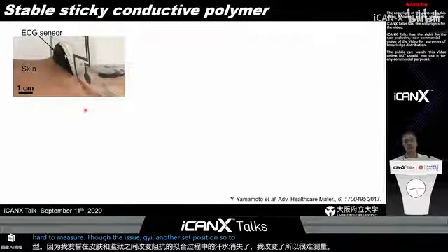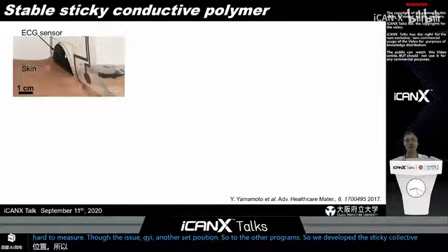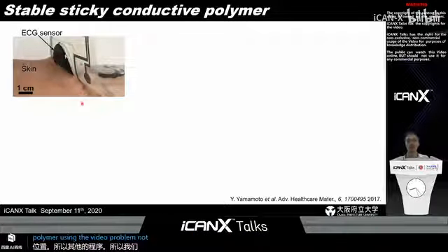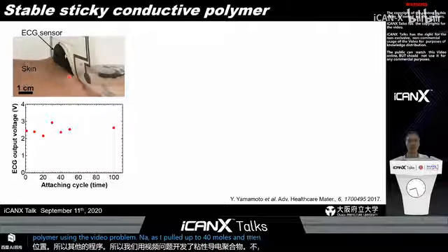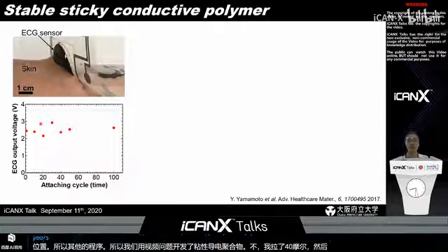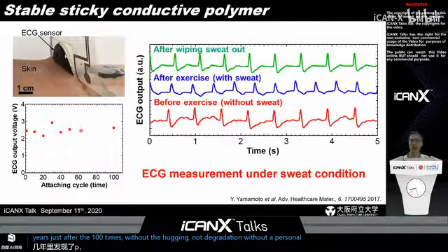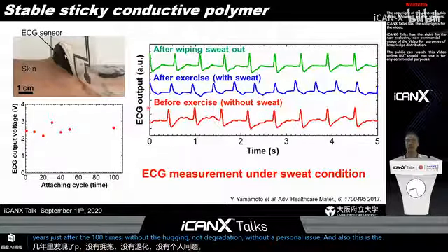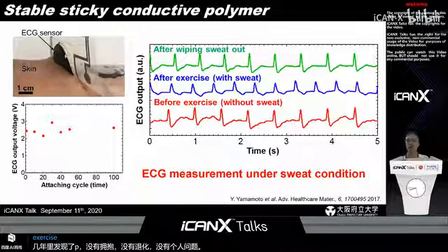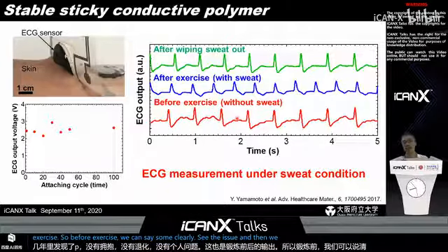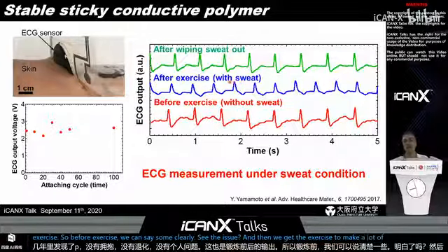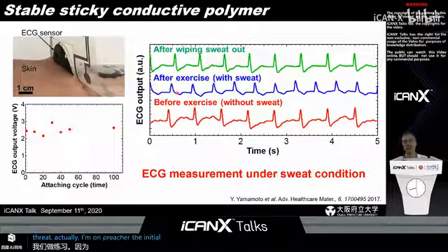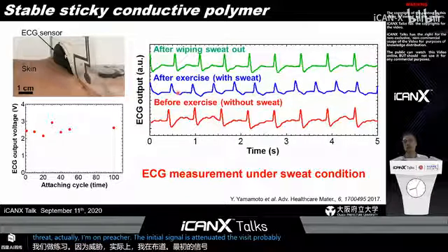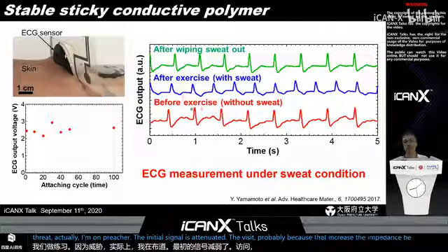To address that problem, we developed a sticky conductive polymer using PDMS and carbon nanotube as conductive polymers. By developing this device, we can repeatedly use this sensor up to 100 times without any large degradation of the ECG output signal. This is the ECG output before and after exercise with sweat. Before exercise, we can clearly see the ECG signal, and then we did the exercise to make a lot of sweat. Due to the sweat, the amplitude of the ECG signal is attenuated. This is probably because sweat increases the contact impedance between the skin and the conductive polymers.